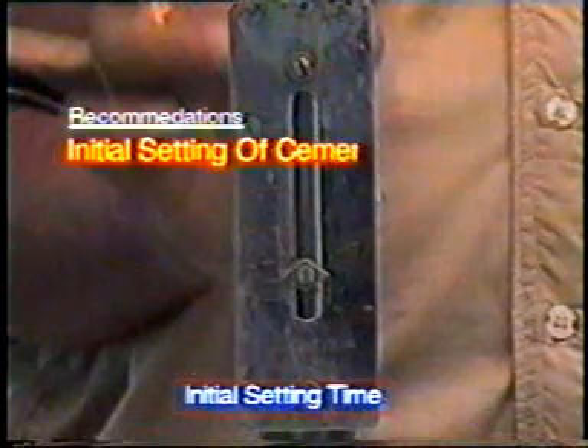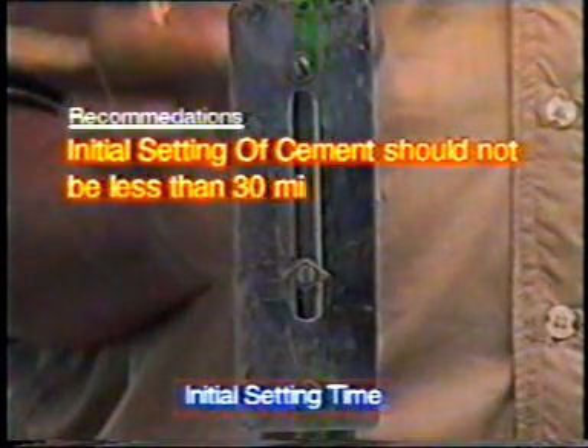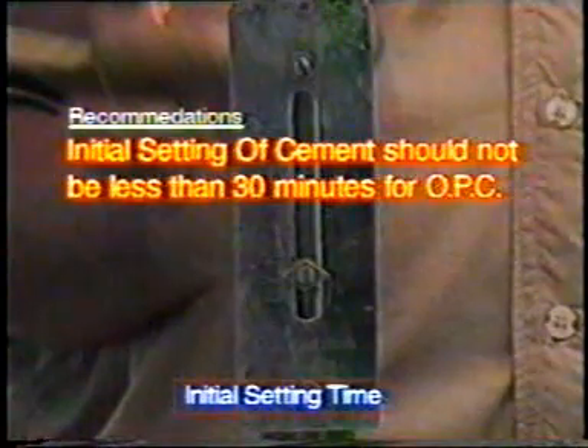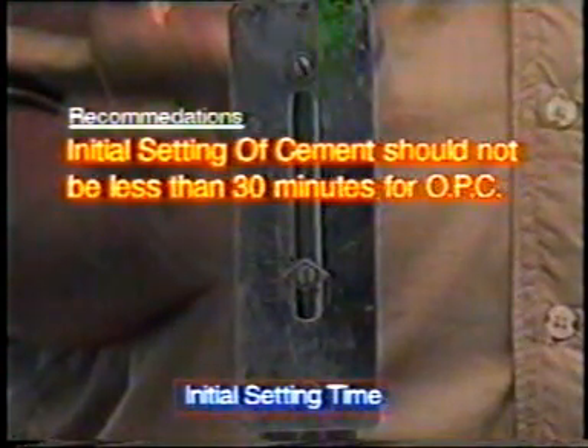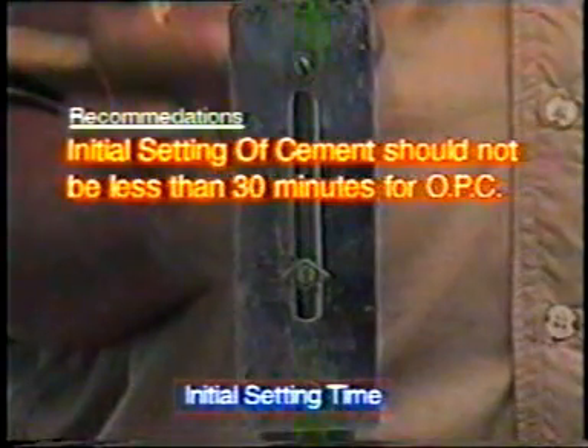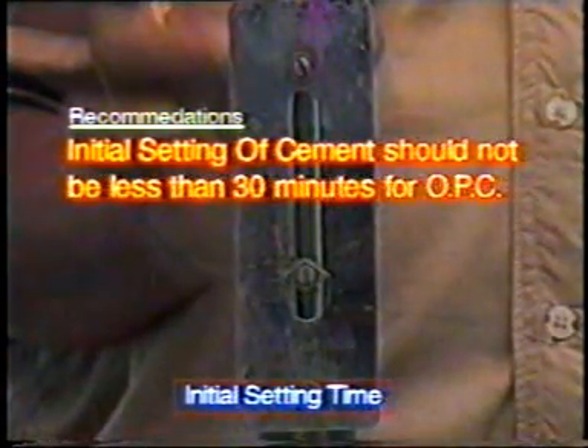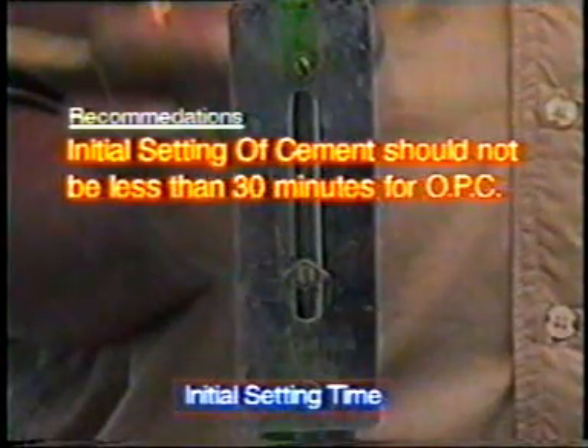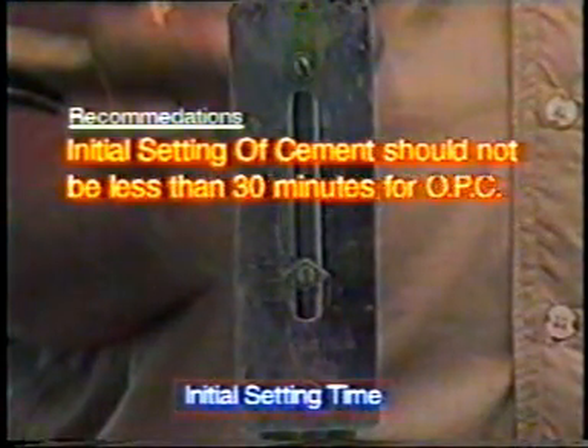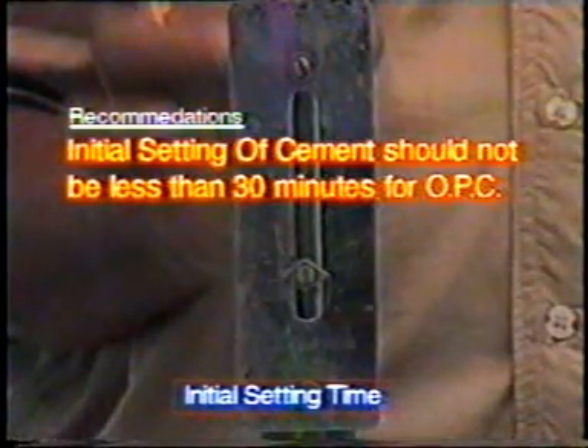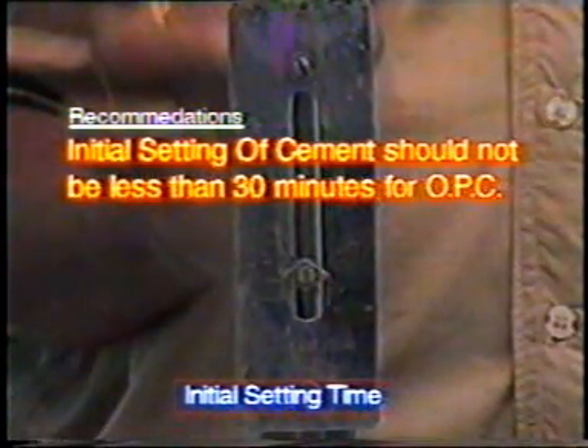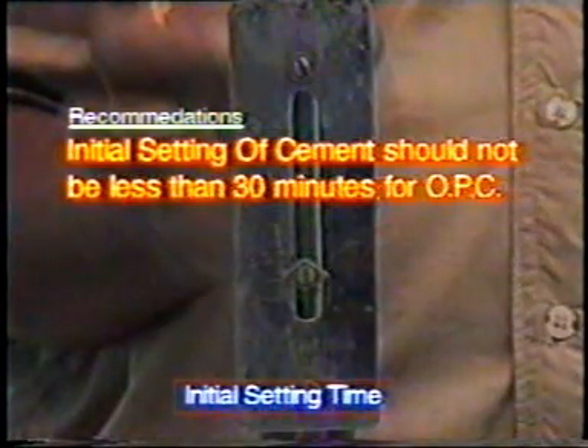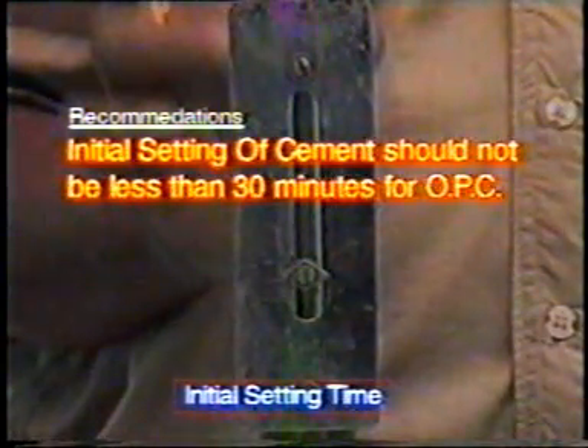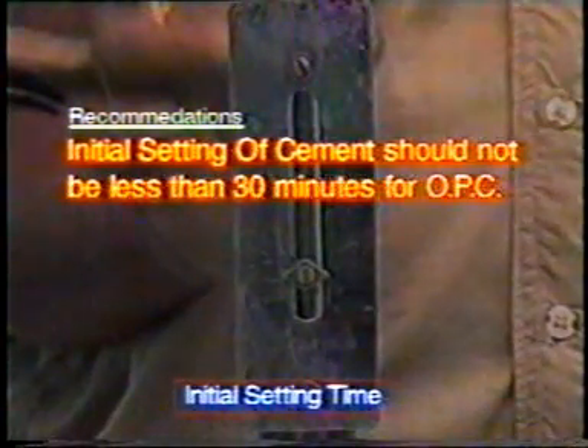Result. Report the time elapsed between the moment that the water is added to the cement to the time when the needle fails to pierce the test block, as seen above, as the initial setting time of cement. That is the time available for mixing and handling operations to be carried out in the field. Recommendations. The initial setting time of cement should not be less than 30 minutes for ordinary Portland cement.